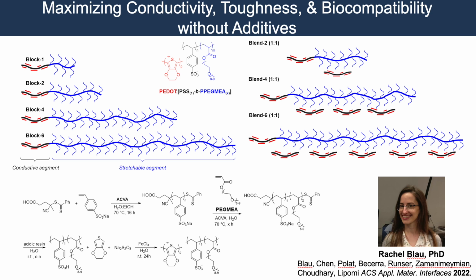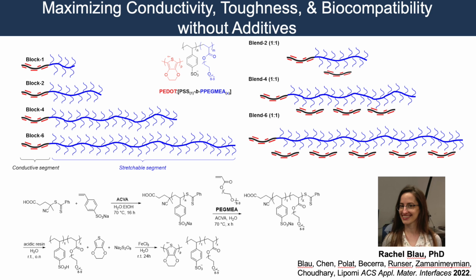And the fact that this big chain here is linked by this covalent bond here means that you're not ever going to be able to phase separate these two structures, because this block copolymer serves as a compatibilizer between this soft segment of ethylene glycol acrylate and these relatively hard segments of P-dot. So that turned out to be a very important consideration.